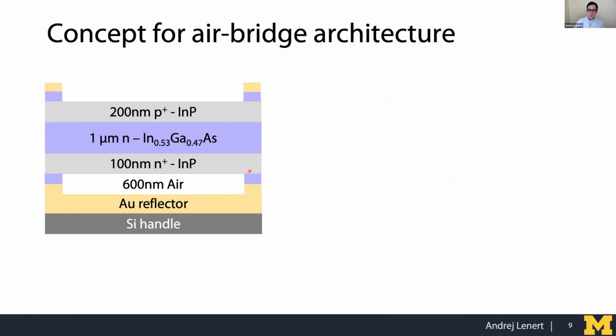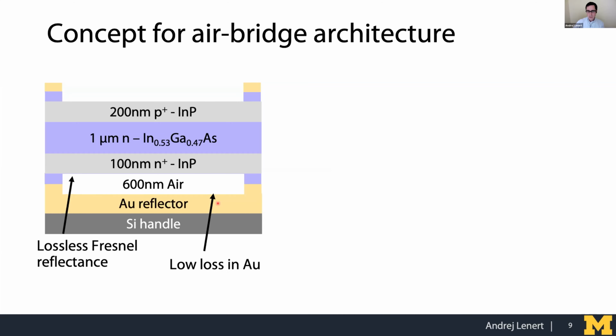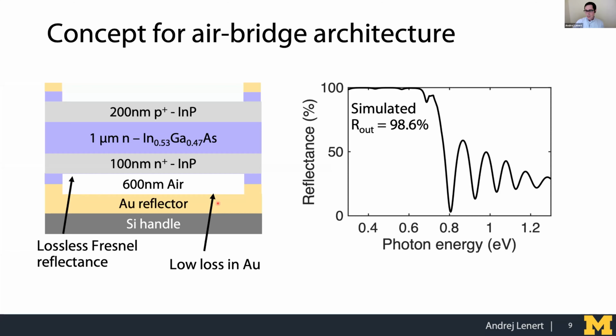So we came across this bold idea of trying to replace the dielectric spacer with nothing. And when I say nothing, I mean air. So try to put a small air cavity between the absorber and the back gold reflector. Now this architecture, this air bridge architecture as we call it, can achieve lossless Fresnel reflectance at each interface. Air is, in a way, an ideal dielectric. It doesn't absorb, and it maximizes the difference in refractive index between the semiconductor-air interface and the air-metal interface. And so overall, we can achieve very high reflectance. And simulations show that that reflectance can approach 99%.